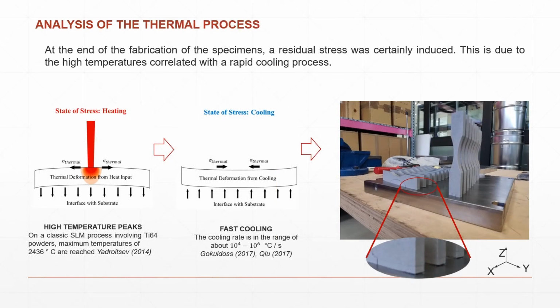Another factor that we have to analyze for its important influence on the fatigue strength is the residual stress. At the end of the fabrication of the specimens, a residual stress was induced. This is due to the high temperatures correlated with a rapid cooling process, characteristic of the additive manufacturing process. Starting from high temperature peaks, for example, in a classic SLM process involving titanium powders, maximum peaks are 2436 degrees. And after that, we have a very fast cooling. The rate is in the range of about 10 to the power 4 to 6, so a very fast cooling.